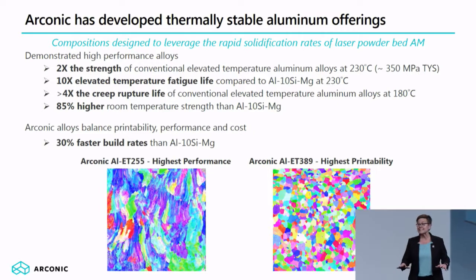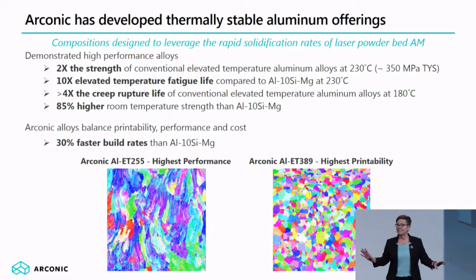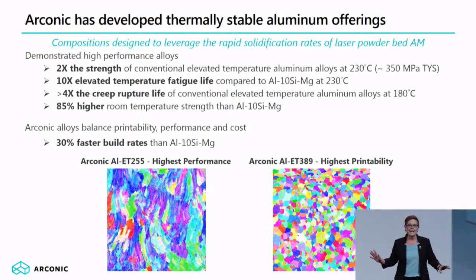Now, when complex geometries are critical, one can choose our ET389. That alloy has exceptional printability and also delivers elevated temperature performance and thermal stability. Both alloys can be printed at 30% faster speeds than typically used for aluminum 10 silicon mag.